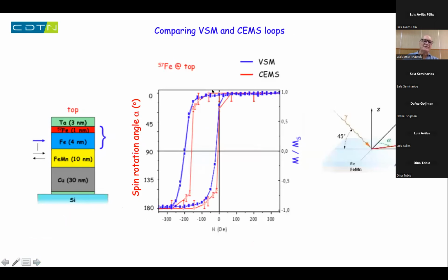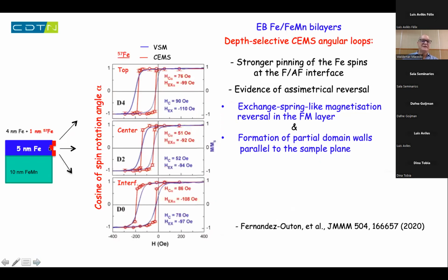The blue line is the average of the sample, the loop from VSM, and the red one is the Mössbauer hysteresis from one position of the iron-57 layer. If we compare the different loops for the iron layers at different distances from the interface, we see that when you go from positive to negative, the reversal is very different. You have a stronger pinning at the interface, and the average represents the VSM loop, and on the top it is much easier to rotate the iron-57 layer than the average of the sample. But when you come back, you see that the reversal is always the same.